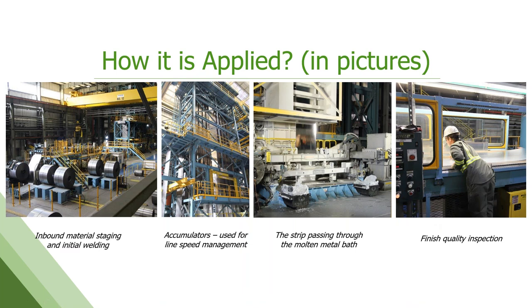These are some pictures of an actual line. So again, left to right, steel coils being staged for entry into the line. Then the accumulators that take up the slack or let it out so we can run continuously. In the Steelscape world, these are vertical and they're about 8 to 9 stories high. Some lines are horizontal, different ways to construct. This picture in the middle here going through the molten bath, that shiny reflective surface you see is the metallic coating right after it's applied to the strip. The bar that says Kohler there and the one that sits above it are the air knives that are controlling the coating weight. And then the cooling starts in this structure right above it. And then we do a bunch of final QC and inspection processes at the end.